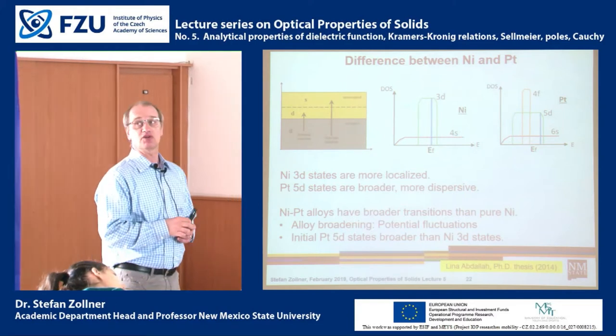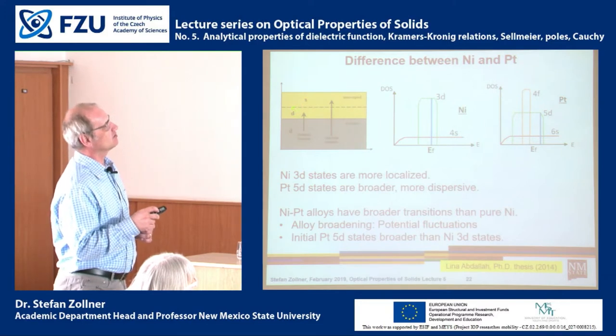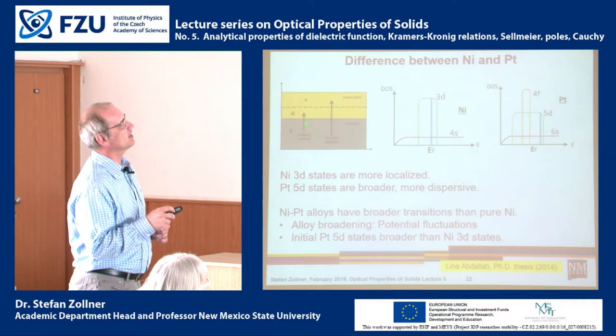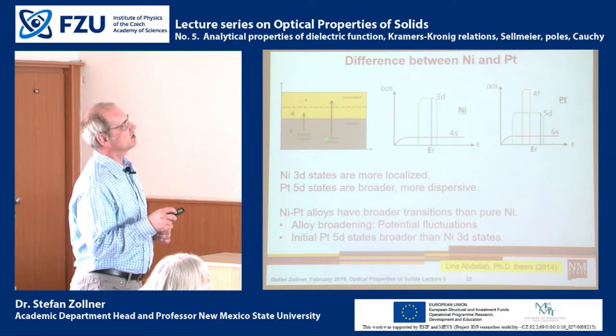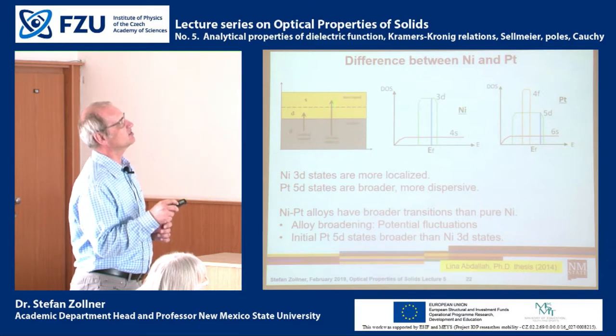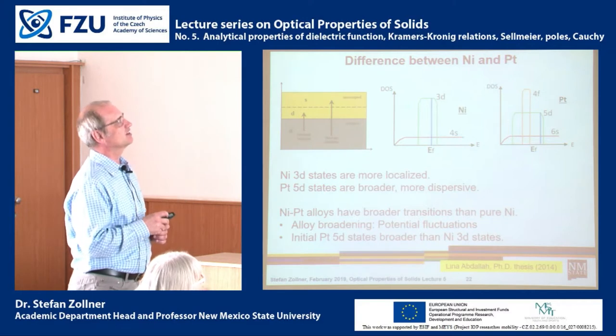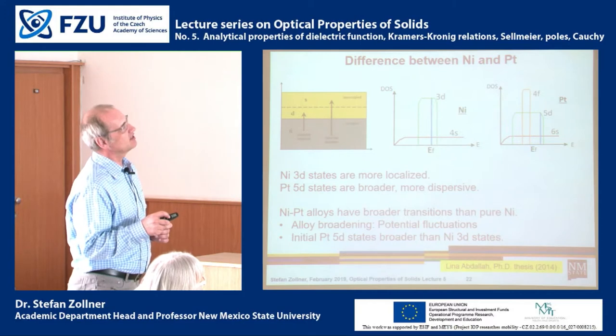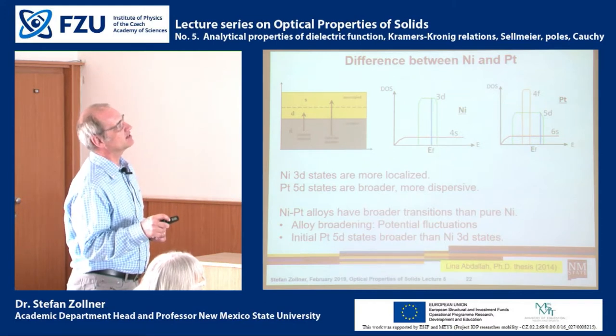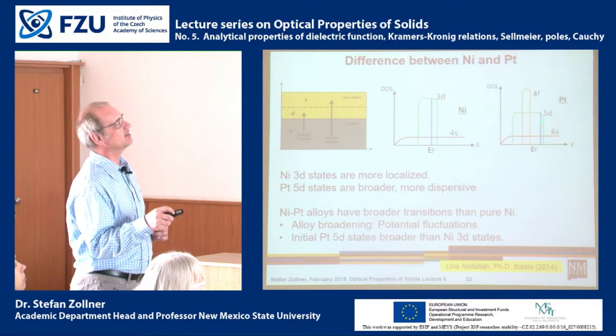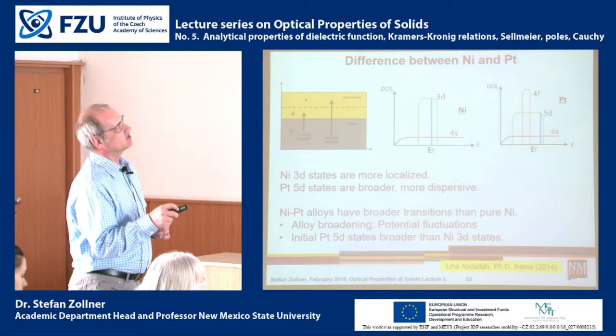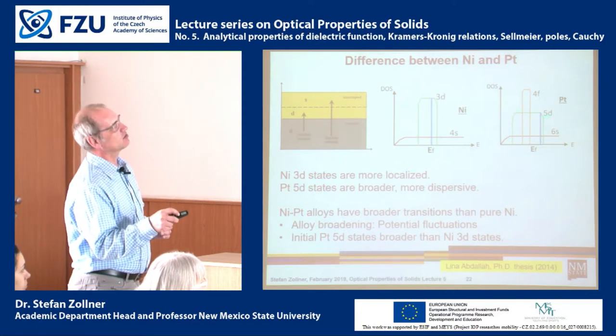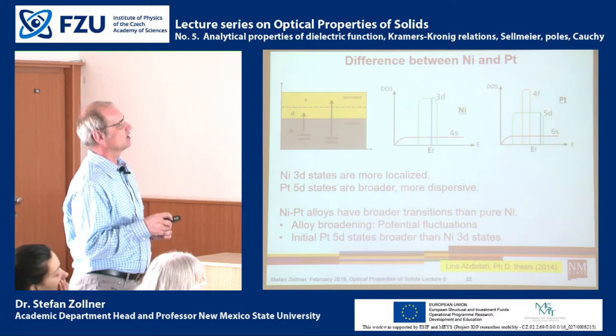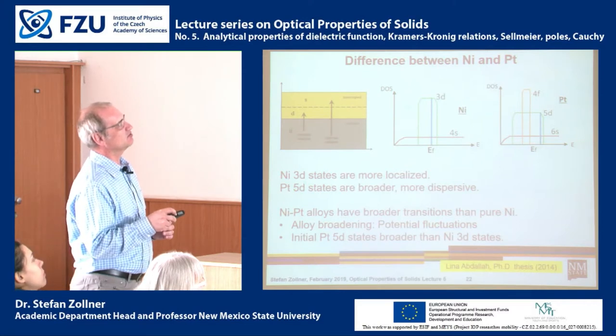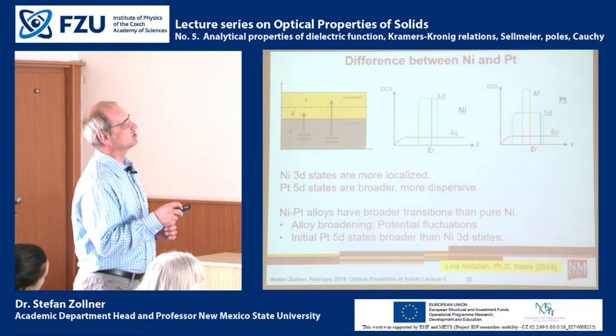Nickel and platinum are both near noble metals. And that's the picture I showed before, that in nickel and platinum we can have d intraband transitions, and we can also have interband transitions from the d states to the s states. So both of these effects will show up in nickel and platinum. But what's the difference between nickel and platinum? Well, in nickel we have 3d states, and in platinum we have 5d states, and the 4f states in platinum are entirely contained within the 5d band. But the nickel 3d states are more localized, and the platinum 5d states are broader, less localized, and therefore more dispersive. So we expect that platinum should be broader and nickel should be sharper.